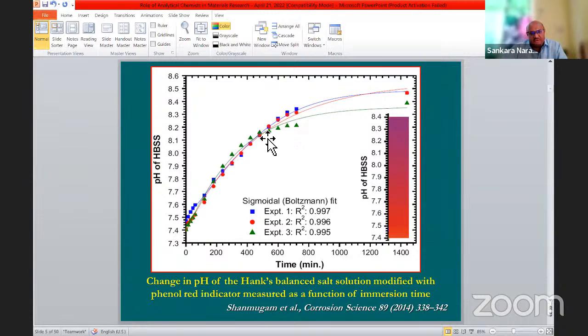Initially there is a rapid change in pH. Subsequently, it tends to saturate, because initially the magnesium is freely available, all sites are available, and it is freely corroding. With time, when it reaches around 800 minutes, a corrosion product forms and the surface is covered with magnesium hydroxide. As I said, there will be an increase in pH at the metal-solution interface, so magnesium hydroxide forms. Once the metal surface is covered by magnesium hydroxide, the rate of increase in pH saturates. It reaches around 8.4 at 1400 minutes. So this is the color change from the initial to the final, about 1400 minutes.